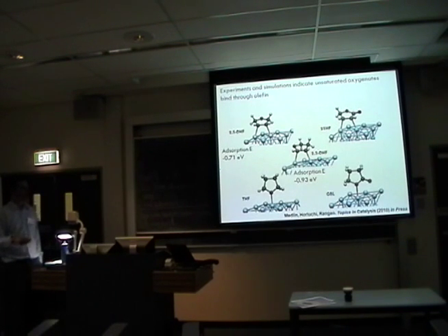So if there is no carbon-carbon double bond, then the reaction always takes place through the oxygenate functional group. That's how the molecule comes down and binds, and that's the point at which it breaks open. If there is a carbon-carbon double bond, it's pretty much always the case that that's what comes down and sits on the catalytically reactive surface first. So that's where the initial reaction takes place, although as we heat the surface up, we can also get some ring opening reactions of the oxygen containing functional group.